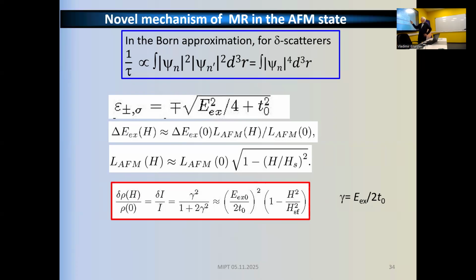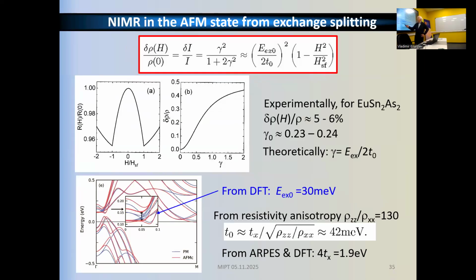And it can be written here even from thermodynamic type arguments like this, and finally you get the magnetoresistance, which gives you a parabolic dependence, and the prefactor is the ratio of what I said, exchange splitting to transfer integral. So depending on the ratio in various materials, you can get it smaller or larger. For our case, according to experiment, in our materials, the amplitude of the effect is about 5 to 6%, so we are located somewhere here. But it can be greater or smaller depending on the exchange splitting in the band structure.